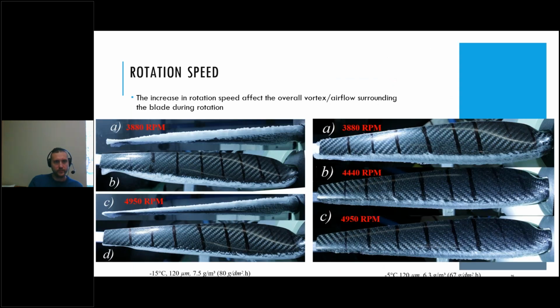What was observed is that the increase in rotation speed seems to affect the overall vortex airflow surrounding the blade during rotation. So that's something that we want to go further into details. We want to study further this phenomenon. Those were only preliminary tests, but we see the evolution of the ice accumulation, especially toward the tips, as we increase the rotation speed, explaining why there's lower degradation at higher RPM. So there's much less ice, especially toward the tip of the blade.